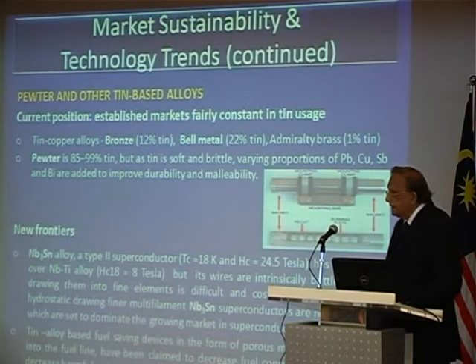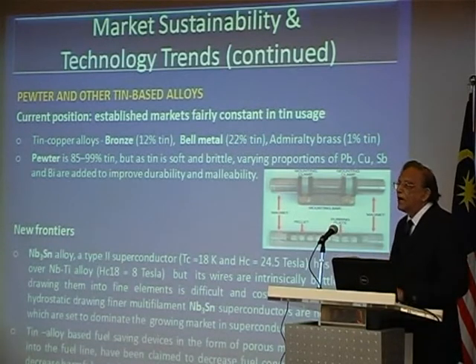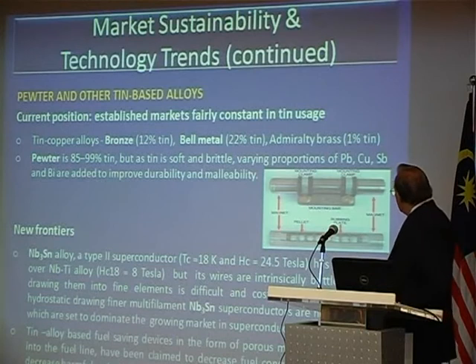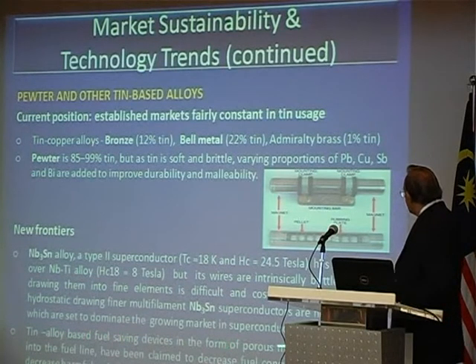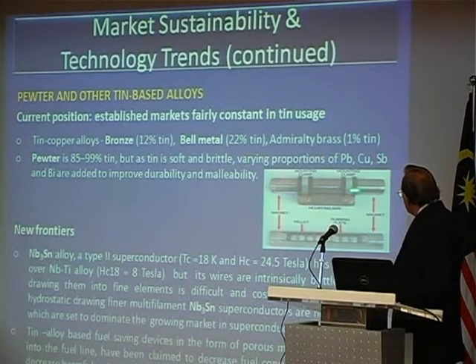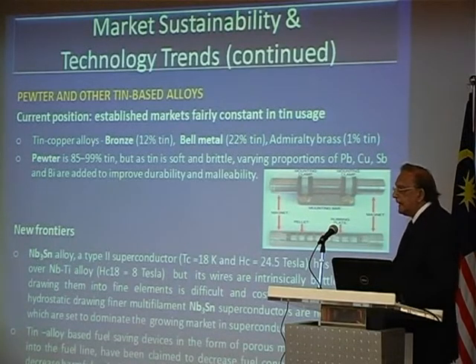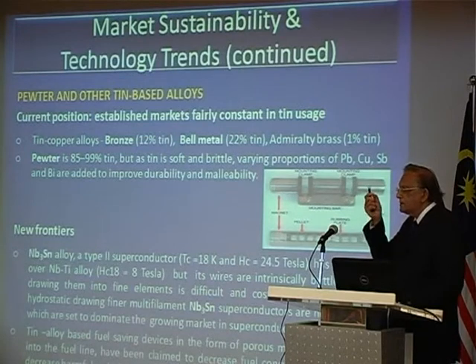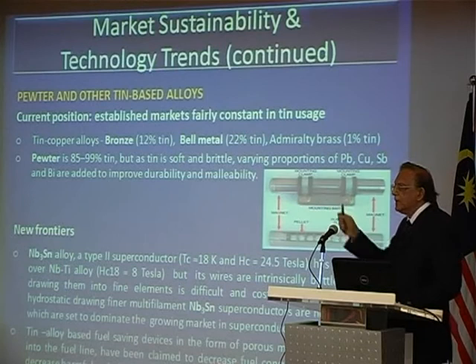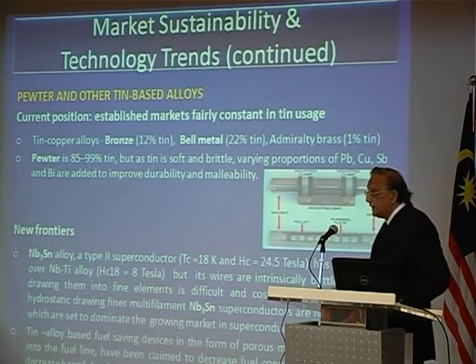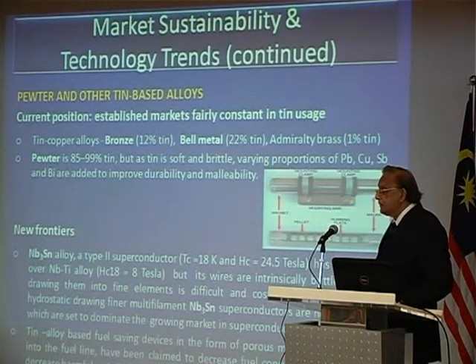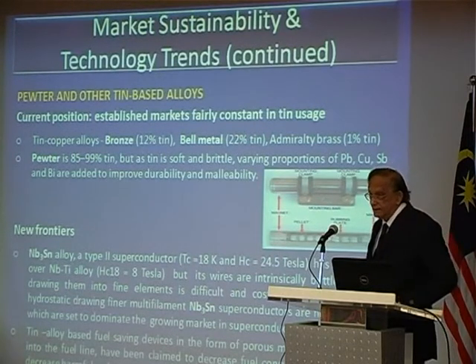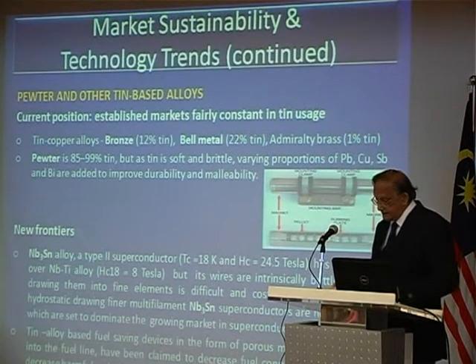Let's go back here. One controversial application, still we are not sure how it works, but some will swear it works, and that is the use of tin alloy-based fuel-saving devices as porous metal pellets. Now this is a stainless steel high-pressure chamber. You have neodymium magnets at either end, and in between you have tin pellets, and then you have rotating blades there, which break up the tin pellets. And small, minute, microscopic particles of tin go into the fuel and somehow influence the combustion characteristics of the fuel, and you end up saving fuel. As a scientist, I will not accept the argument that the magnetic field somehow breaks up the long chain hydrocarbons into smaller chains. But there is a potential here, and there's a market as well.